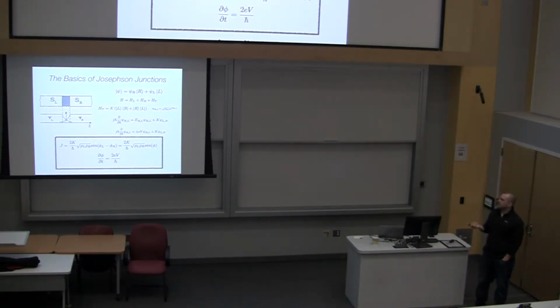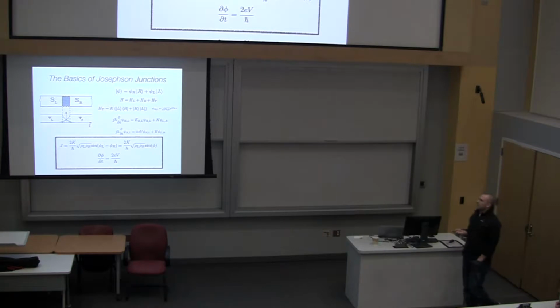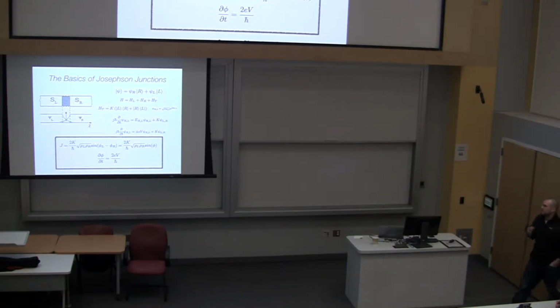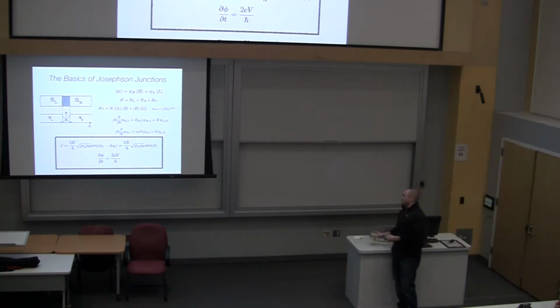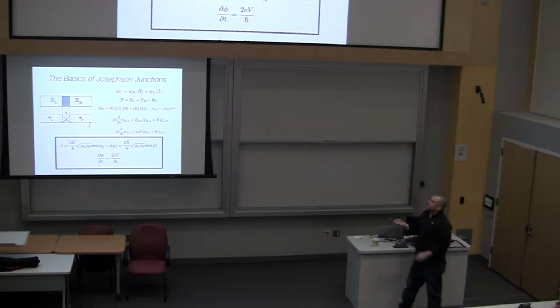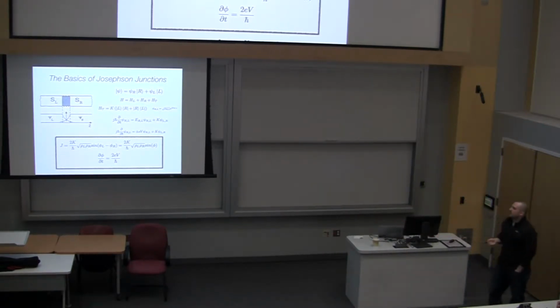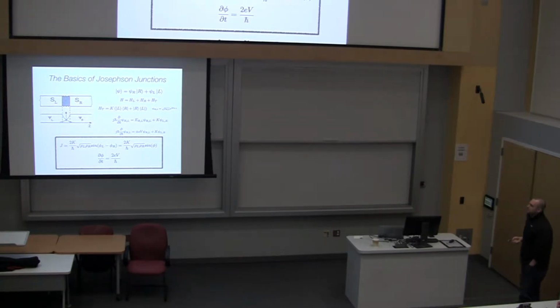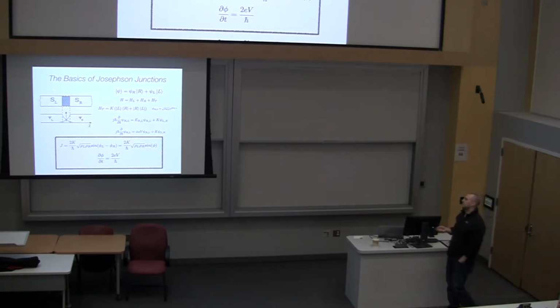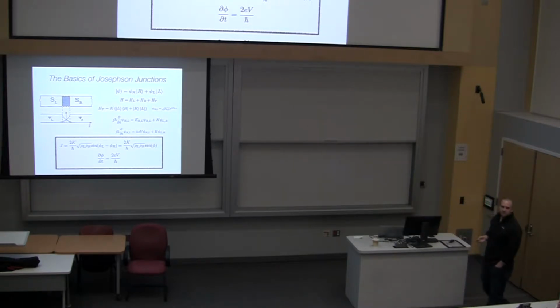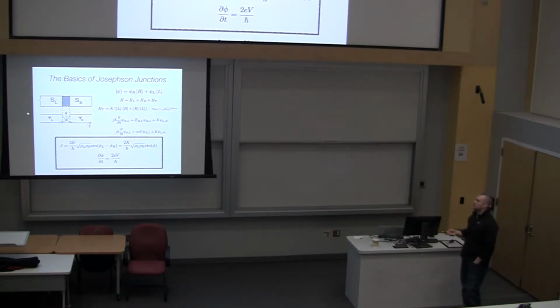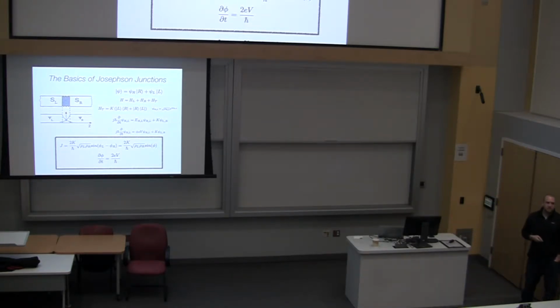A Josephson junction is basically two superconductors that are separated by some material that's not superconducting. Traditionally, this falls along the lines of an insulator like aluminum oxide, which separates two superconductors on the right and the left. Each one of these superconductors has a wave function or order parameter associated with it. Since Cooper pairs are not allowed in this insulating barrier, that wave function will decay exponentially. If I bring these two superconductors close enough together such that they can start to talk to each other, this overlap allows a supercurrent, or a resistanceless flow of Cooper pairs, between the two leads on the left and the right.